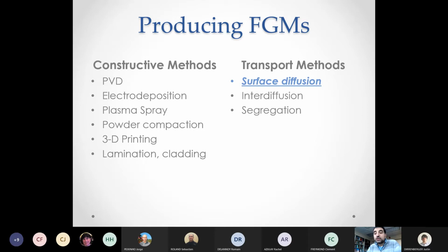And of course, there is the more traditional approach of lamination or cladding, which gives multi-layer materials. So these methods depend on changing the composition as we build the material. We can also think about methods where we depend on diffusion, so transport methods. The most obvious example is surface diffusion, as in the case of carburizing or nitriding of a steel. But if we're creative about it, we can even think about segregation as a way of patterning a fine scale composition gradient within the material.